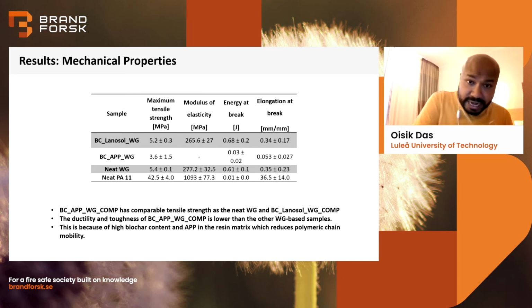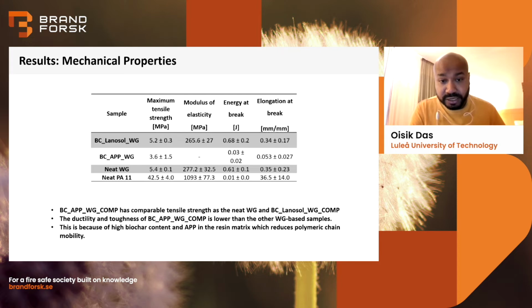And then we have also analyzed the mechanical properties, and we can see that the APP doped biochar in wheat gluten made by compression molding has similar tensile strength compared to the Lanosol doped biochar, which is good because this is what we are trying to conserve, the mechanical strength.